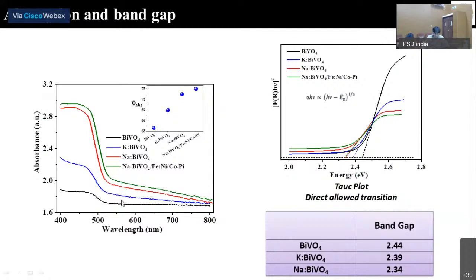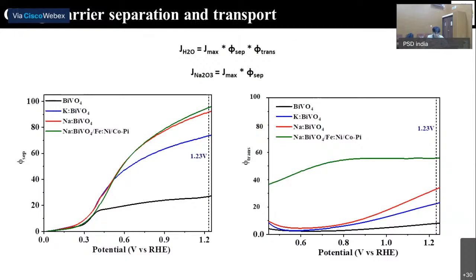Further, we have confirmed in later experiment. And if we see the band gap, which is calculated using the Tauc plot, band gap is decreasing. These are the experimental results. That means the improvement in absorption that we are seeing might be due to the reduction in the band gap. Then next comes our charge separation and charge transport efficiency.